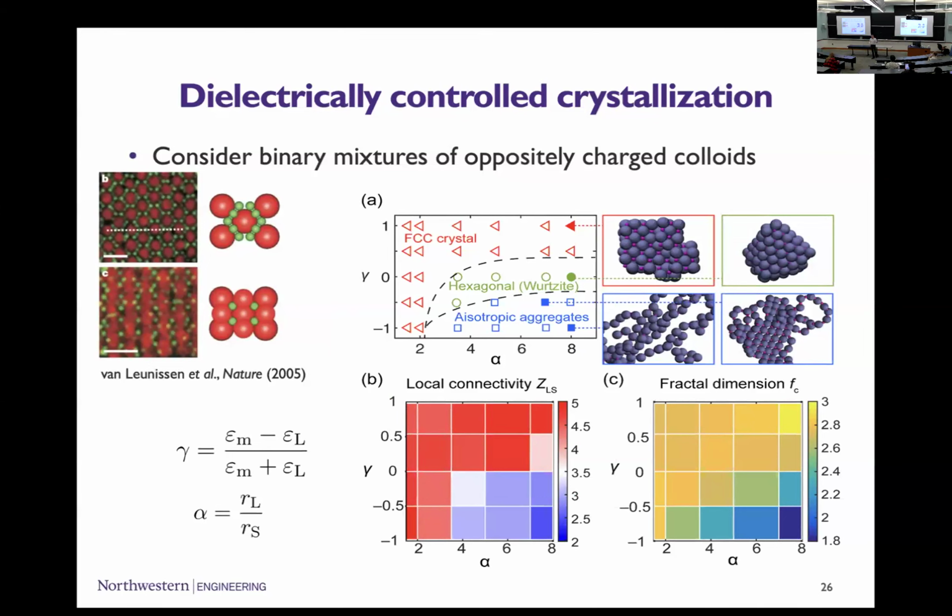Mathematicians have labels for them, but they cannot be made with atoms because the size ratios do not exist between atoms. And there are lots of interesting structures, like for example, situations where 4 small particles dot one side of a big sphere and then another sphere comes in, right? So every junction point is surrounded by lots of small particles. And I realized, if you now include dielectrics, polarization, you should get even more crystal structures. But that's hard, and it's now a problem we can address, but only because we have this super fast algorithm.